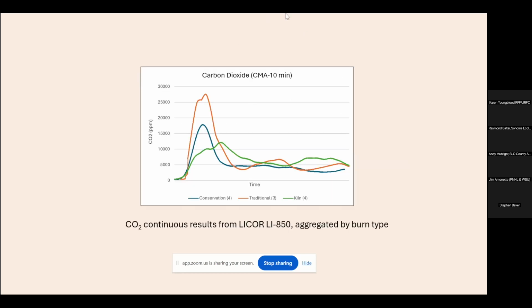Okay, so here are some of the results. Here's a real-time look at CO2. The first thing that jumps out is that very high peak there of over 25,000 ppm of CO2, and that represents the flaming phase. For the traditional piles, the conservation piles were a little lower, and then the kilns were quite a bit lower. The kilns obviously burn in a different manner than the piles do. And you can see as the fire burns down, CO2 concentration decreases.